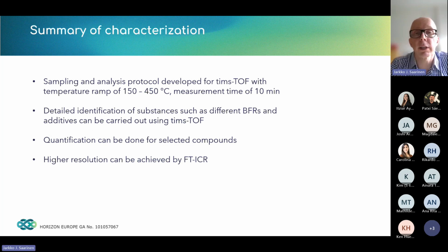So to conclude and summarize the characterization part, in this Primus project, we have been developing the mass spectrometry tools, the sampling and analysis protocol for the timsTOF device, so that we can do the temperature ramp from 150 C to 450 C. And within the measurement time of 10 minutes, we can very accurately detect the different compounds in an unknown recycled plastic sample. So very detailed identification of different substances, such as brominated flame retardants, substances of concern and very high concern, and also the non-intentionally added substances can be detected. As mentioned, the quantification can be done for selected compounds, and we can also achieve a significantly higher resolution using our 12 Tesla FTICR in the case that is needed.